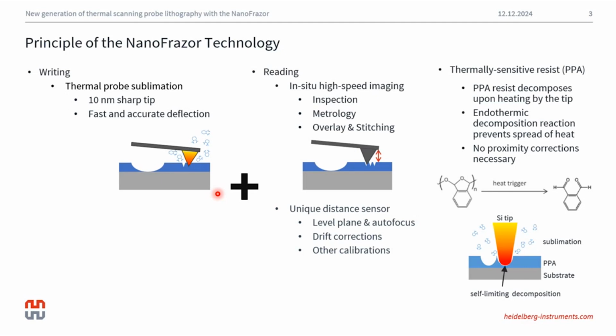In this case, upon contact with the thermal resist PPA, the resist right under the tip readily sublimates, and this is an endothermic decomposition reaction, which means the heat is not uncontrollably spreading on the PPA layer or on the substrate. In addition, we don't need any proximity corrections for this lithography step, and because the PPA is sublimating directly, we don't need an additional development step, as is usually the case for photolithography and e-beam lithography. When it comes to resolutions with writing into PPA, we can reach around 10 to 15 nanometers of lateral resolution and also a single nanometer in vertical resolution.